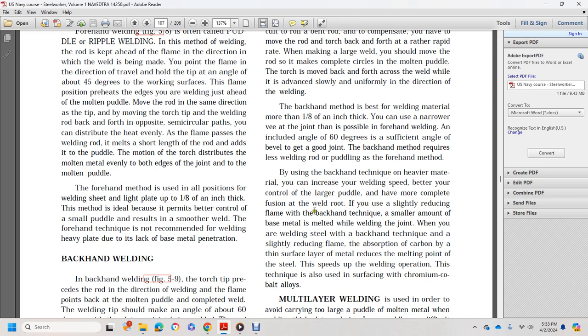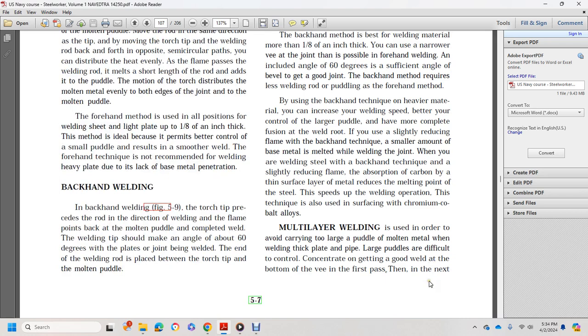If you slightly reduce the flame with the backhand technique, a small amount of the base metal melts while welding the root joint. While welding steel with a backhand technique and a slightly reduced flame, absorption of carbon into the thin surface of the metal reduces the melting point of the steel, increasing the speed of the welding operation. This technique is used in surfacing with the chromium cobalt alloys.